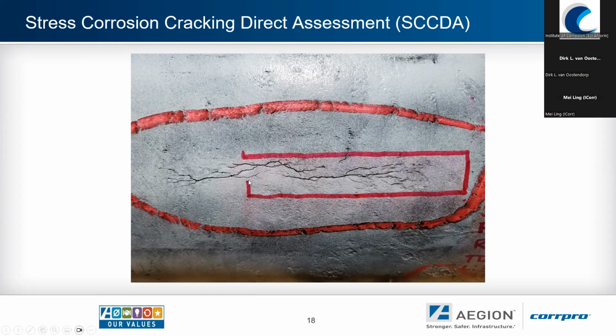The good news is the cracks had not coalesced to failure point, but it was quite encouraging to be able to identify it this accurately. And the pipeline operator ultimately ended up having to cut this section of pipe and do a replacement because composite reinforcement wouldn't have satisfied the mechanical requirements at this location.